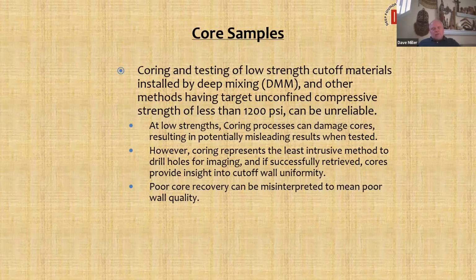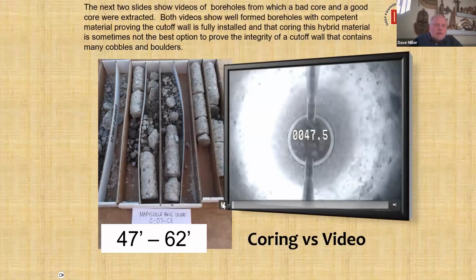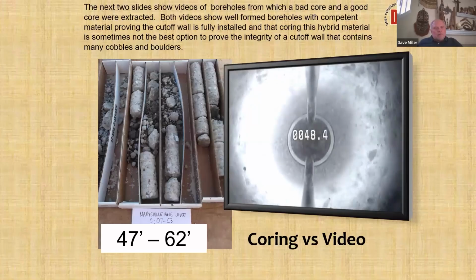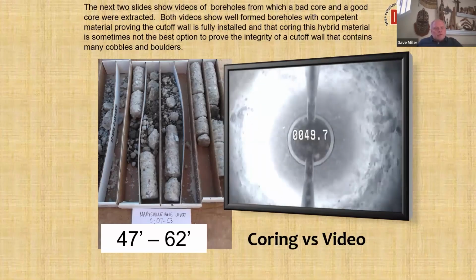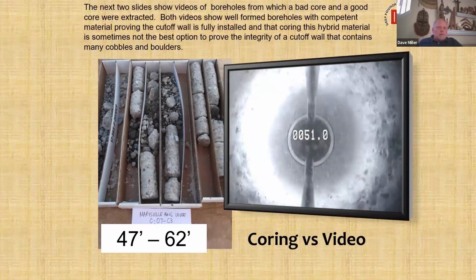The coring process can lead to microfracturing, rendering the core unusable. Even though it can look great, the microfractures may not allow it to break. It will create a failure plane along the fracture. And gravels especially are difficult to core because they can break loose and just tear up the matrix completely. Okay, so here's an example of a couple of cores. This one doesn't look so great. You see a lot of gravels in it, and maybe, first impression, it's not well mixed. But if you take a video of that and you look at the side walls of this video, you can see there's a lot of gravel and particles within the sidewall. It's all bound up within the matrix.